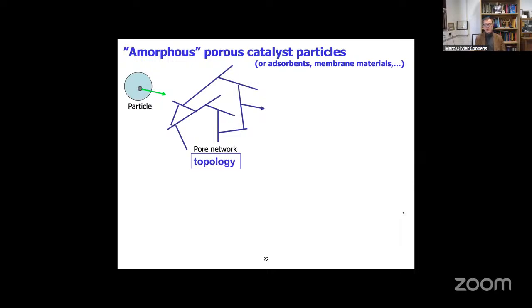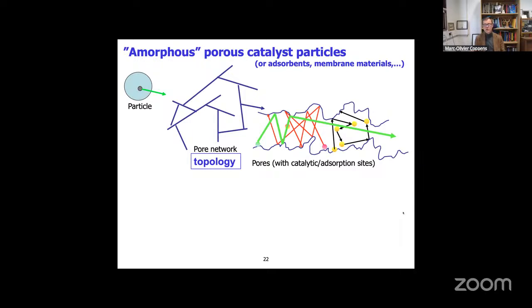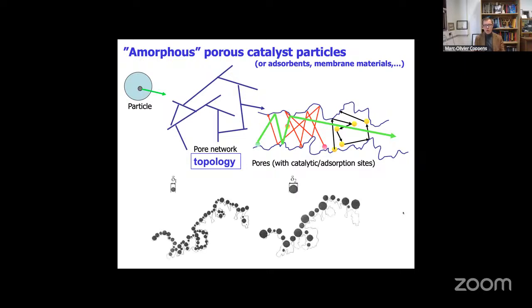And so if we look back at our image of a catalyst particle, we have on the one hand the pore network, which says something about the topology. And these pores might be, say, cylindrical pores or spherical pores, or they might have a certain degree of roughness, and they might contain catalytic and adsorption sites. And so we can zoom in again and invoke how the molecules are interacting with the surface, and where perhaps small molecules can see much more of the surface than larger molecules, which can't access the whole surface. And as we will see, this has an important influence also on transport properties. So this is a factor of morphology. It is really about shape. So the overall description of these particles is a combination of looking at how pores are connected, or how particles with their pores in between are connected with each other, and then shape factors, which are related to morphology.